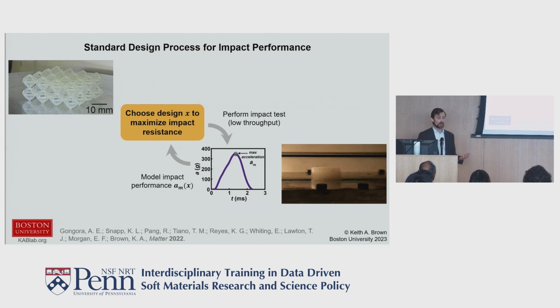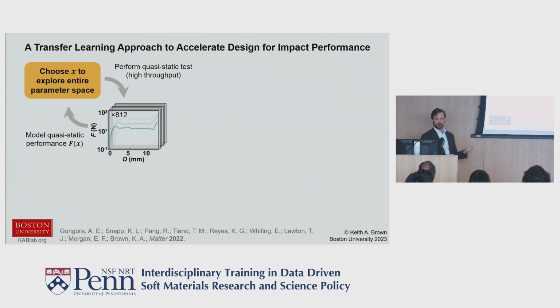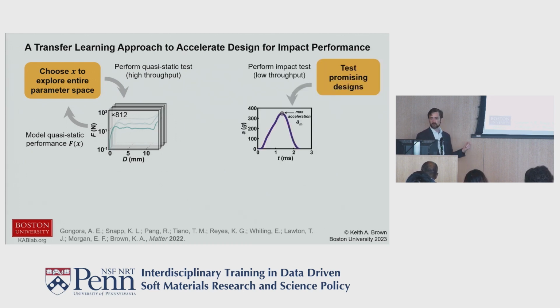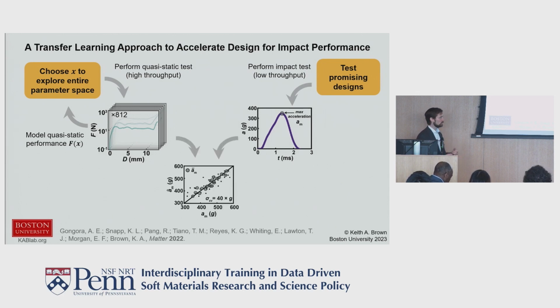Well, we have to leverage the fact that we have a huge amount of data that's collected by other means. In particular, we developed an approach where we take the same parameter space and test using a high throughput method, quasi-static testing, which we can do robotically. We can generate hundreds and hundreds of curves of different structures in the space, not designed to optimize anything specific, but really just designed to explore the space and get a sense of everything that's possible. We can then select things from this space and test them in the slower process to get this iterative design. And then compare the results to build a machine learning model, which I'll talk more about on the next slide, that describes our predicted performance from quasi-static measurements against what's measured in the impact.